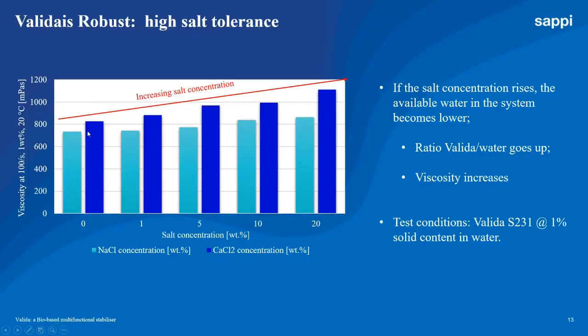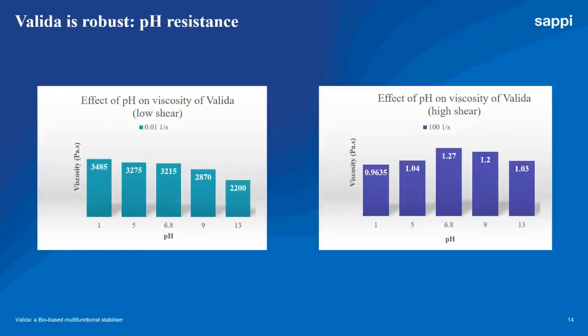Actually, we have noticed a slight increase in viscosity, which is linked to the reduced amount of water in comparison to the amount of fibers in the formulation when increasing the salt concentration, which is a very good aspect. Also, we have analyzed the stability of Valida in the pH range going from 1 to 13, so almost the whole pH range. And we have noticed that Valida shows good resistance in different conditions, acidic and alkaline.